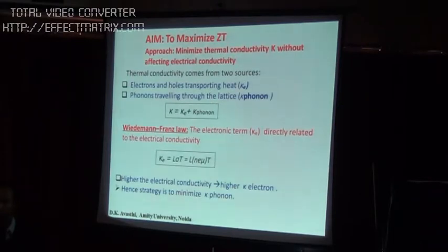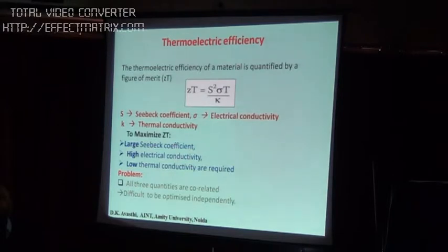The aim is to maximize ZT, and this can be done in this way: the thermal conductivity can be split in this form, the electronic thermal conductivity plus the phononic part. If one reduces only K phonon, then one can reduce K. One can always say, in this formula, if I try to reduce K to increase ZT, then this also decreases, because the thermal conductivity and the electrical conductivity are correlated.